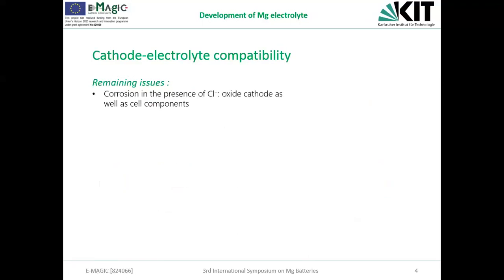So we know that the chlorine has multiple functions in the system, but the corrosion is still the issue there. This is especially the case for oxides, for example, the transition metal oxide, which is still the choice of the market, I would say, in the case of lithium-ion batteries. And also, it's a promising high voltage cathode material for magnesium batteries. So you have to somehow find a way to develop an electrolyte that is at least compatible with this high voltage cathode. Also, the chlorine corrosion issue makes us think that we have to make a special anti-corrosive design in the cell manufacturing, for example. This will add additional cost and effort.